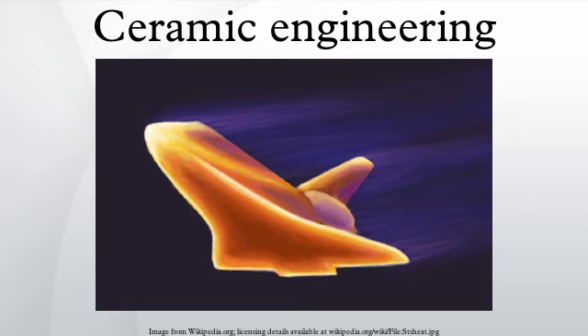The negative thermal expansion coefficient of the crystalline ceramic phase can be balanced with the positive TEC of the glassy phase. At a certain point the glass ceramic has a net TEC near zero. This type of glass ceramic exhibits excellent mechanical properties and can sustain repeated and quick temperature changes up to 1000 degrees Celsius.